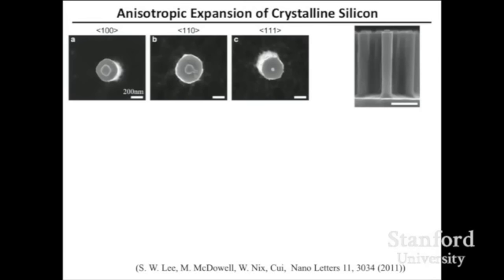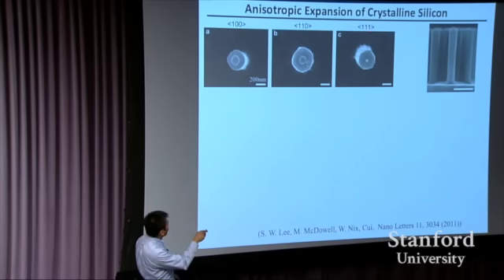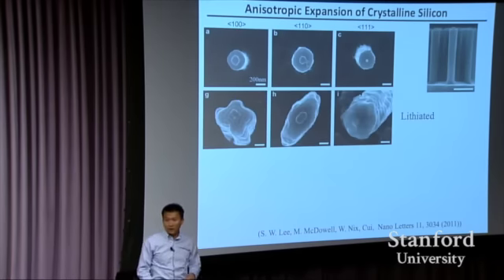And through several years of research, working together with a number of very talented graduate students and postdocs, and also with different expertise and different research groups, we figured out problems one by one. For example, if you ask the question, how does silicon expand? Do they go like this, isotropically? Or is something very different going on? So we patterned pillars with round shape along the 100, 110, and 111 directions. As soon as you put lithium in, you see something dramatic happening.